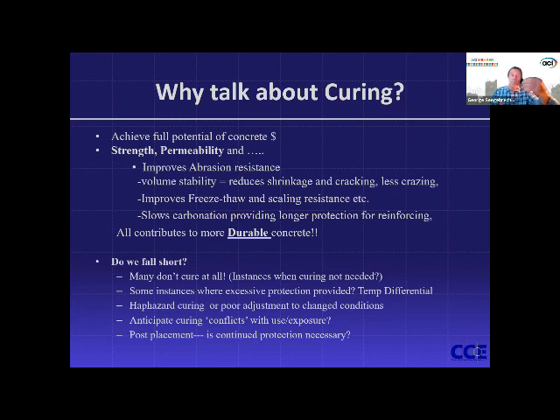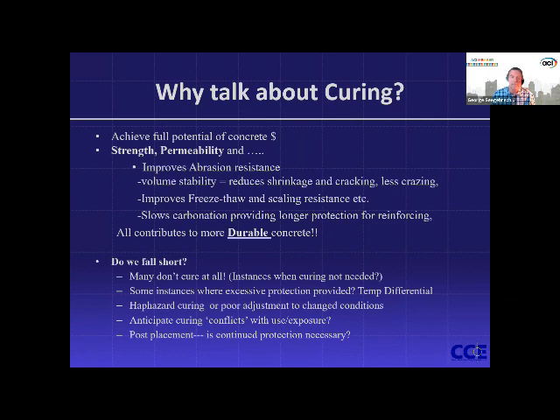And with the reduction in permeability, we get a reduction in, or a slowing of, the carbonation front that is going to come through our concrete, which happens to all concrete. But the longer it takes for that carbonation front to advance to the depth of the reinforcing steel, the better we are. So all of this, bottom line, it all contributes to more durable concrete. There are even more positive benefits of curing that I didn't want to take up more room on the slide for.